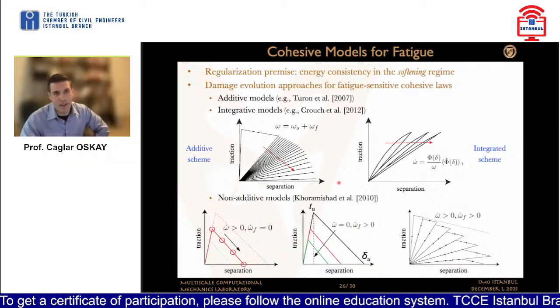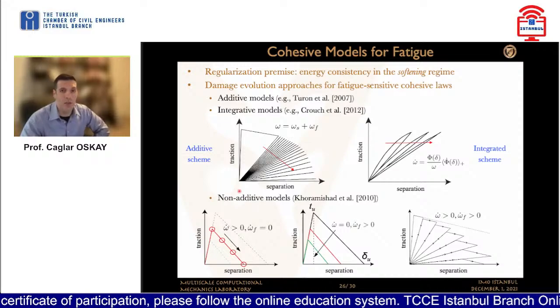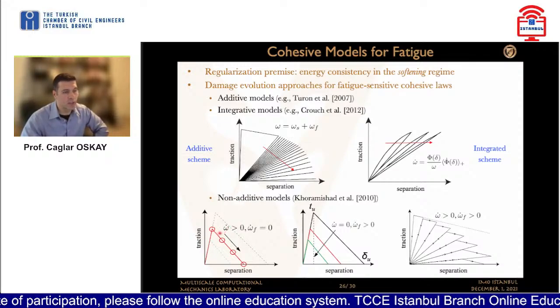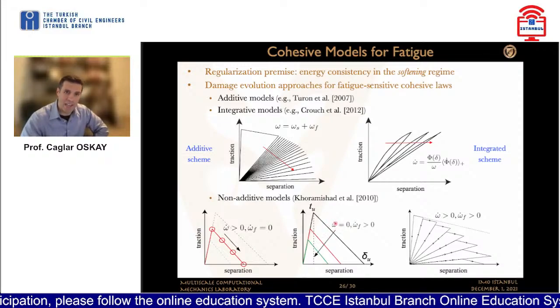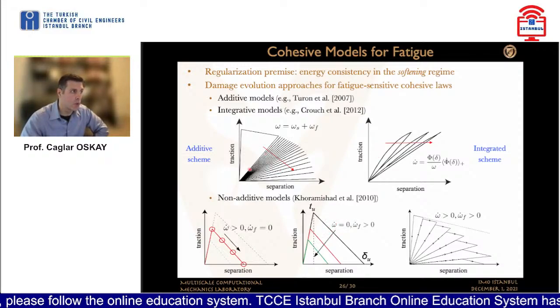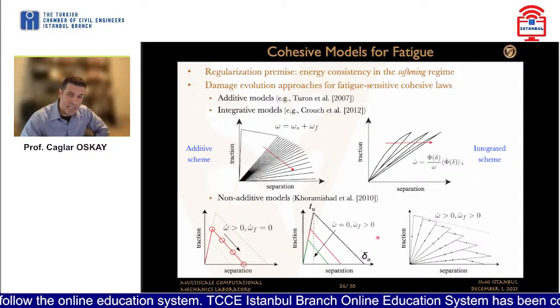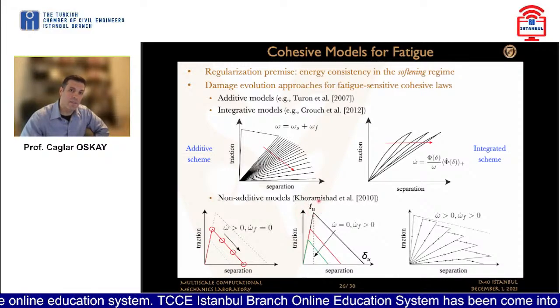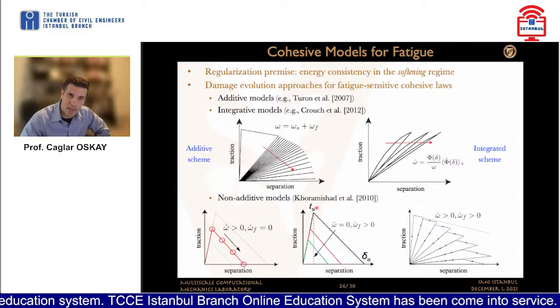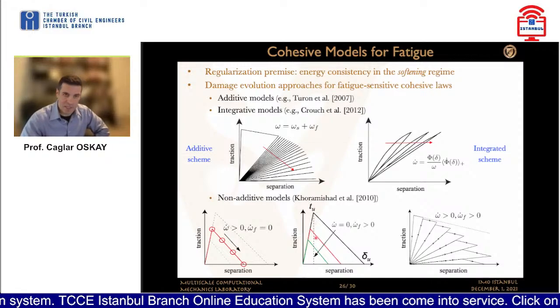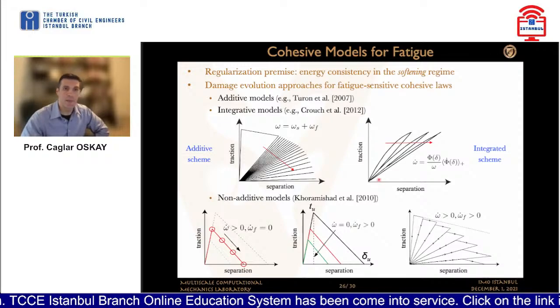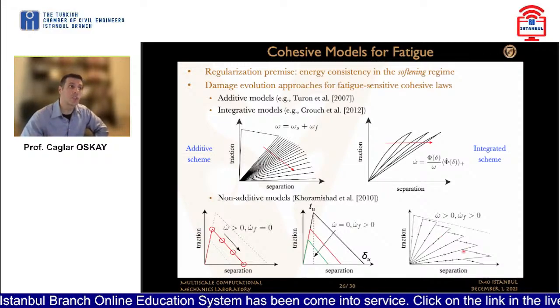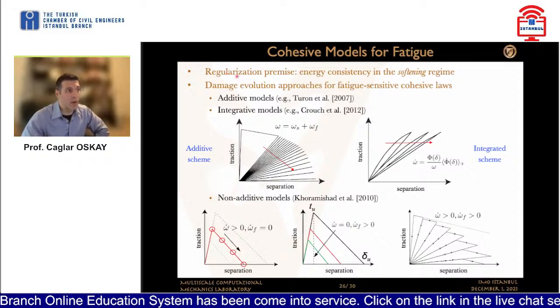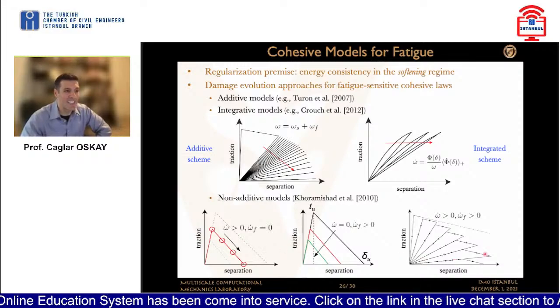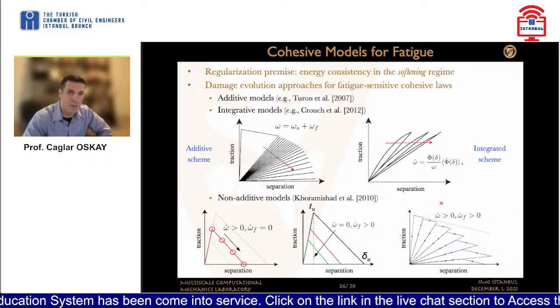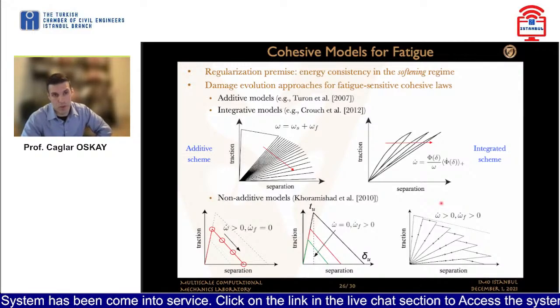What we have done is to consider a different type of cohesive constitutive law, in which the general stiffness reduction is performed for the static case in the standard approach, like we do in the additive and integrated models, but the fatigue damage evolves the ultimate strength and ultimate traction of the domain. By this approach, we allow the system to dissipate energy under fatigue loads in the softening regime, thereby allowing us to regularize the system. So the selection of the cohesive law is very important for fatigue.